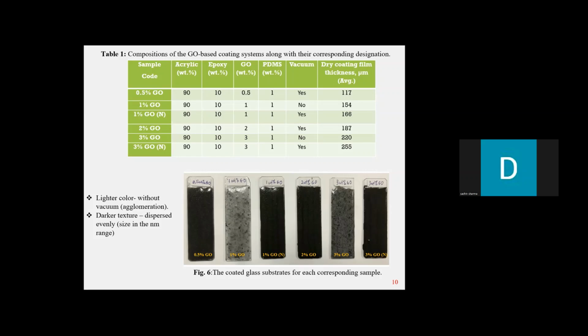As I mentioned earlier during the fabrication process of the graphene oxide, and also in my research objective, we wanted to see how the size of the nanoparticles actually affected the performance of the coating. Therefore, if you can note, for the 1% GO and the 3% GO, only for these two, I prepared two samples each. You can see one is 1% GO and the other one is 1% GO new. One was fabricated without the influence of vacuum, and the other, the new one, was fabricated with the influence of vacuum. Similarly, for the highest loading ratio of 3 weight percentage GO, two samples were prepared, one without the influence of vacuum and one with the influence of vacuum. So over here, we can actually see the difference.